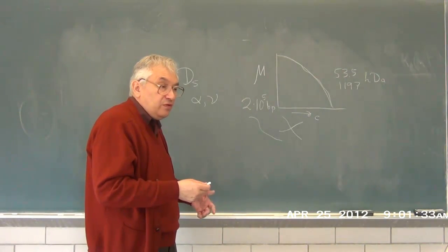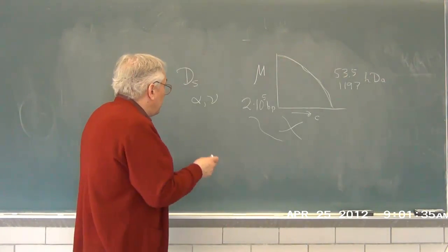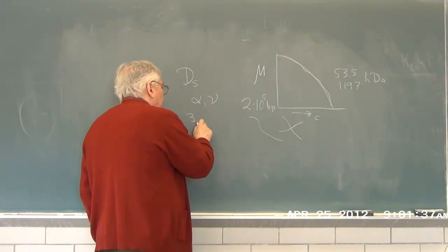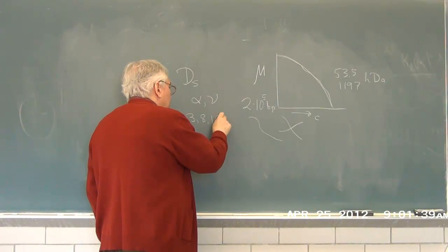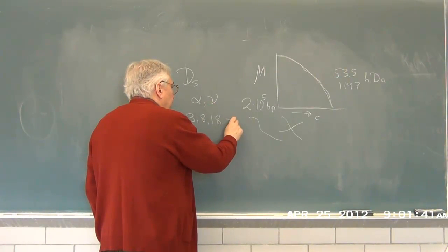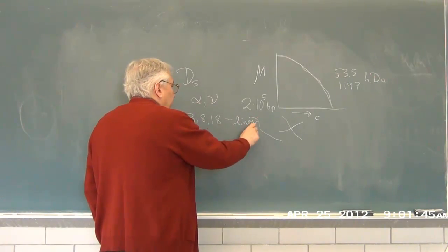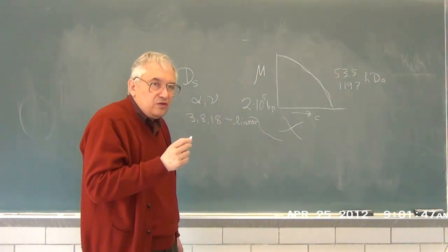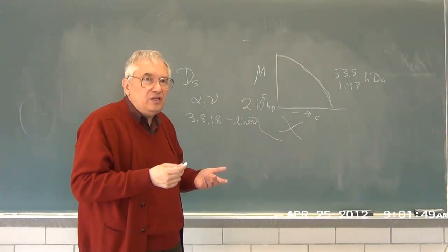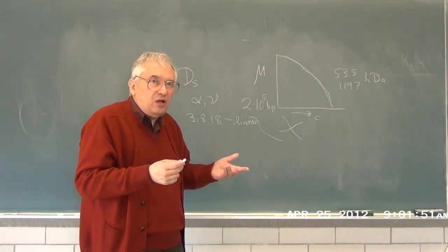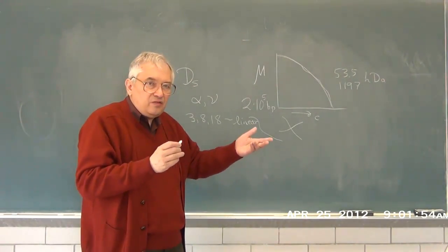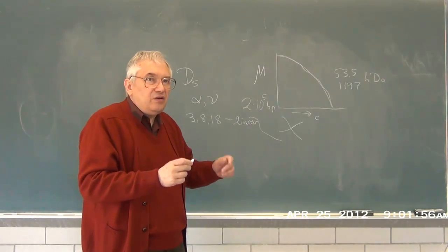If we do probe diffusion, we'll use linear chains and stars. You find for 3, 8, and 18 arm stars that alpha and nu are certainly not very different than for linear chains. I didn't say they're not different at all, but they're not enormously different, as if the star polymers had different methods of propagating than linear chains did.